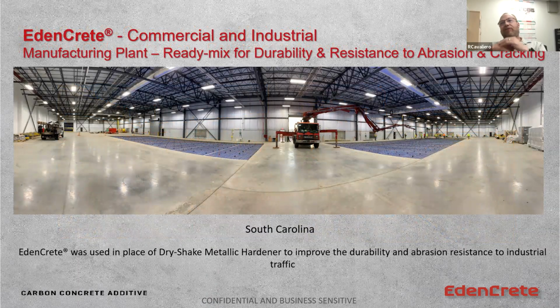Michelin and their manufacturing facilities, this is an extruding facility, and they often take individual sections within the concrete and they use a metallic dry shake hardener. If you're not familiar with a metallic dry shake hardener, it's essentially iron oxide shavings that are embedded with a very finely ground calcium aluminate cement, or a high aluminate cement. So it's a very high strength, fast, high reactivity, thin layer of cement that has metal shavings in it. And that stuff has to be applied after the concrete finishes and the concrete bleeds.